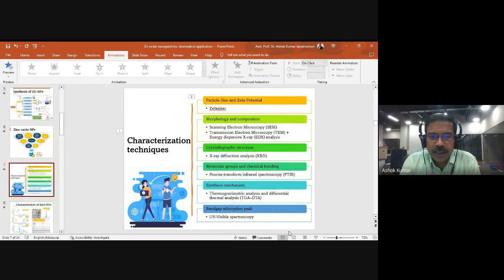So after preparing zinc oxide nanoparticles, we need to do the characterization. We have a lot of characterization techniques to confirm the zinc oxide and the drug which is already encapsulated or absorbed on the surface. The first and foremost analysis is particle size and zeta potential. So we need to check the particle size of the prepared zinc oxide nanoparticles by using the zetasizer. Then the morphology we can confirm through SEM or TEM analysis or EDX, energy dispersive X-ray analysis.